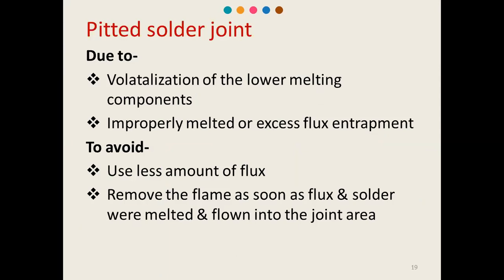Now how does the pitted solder occur? A pitted soldering joint occurs when there is an inclusion of porosities. It is due to the volatilization of the lower melting components, or it can be due to improperly melted or excess flux entrapment. So to avoid the pitted solder joint, we will have to use a lesser amount of flux and remove the flame as soon as the flux and solder have melted and flowed into the joint area, which we have seen in the time consideration during the soldering steps.